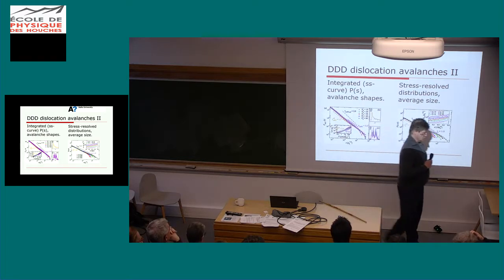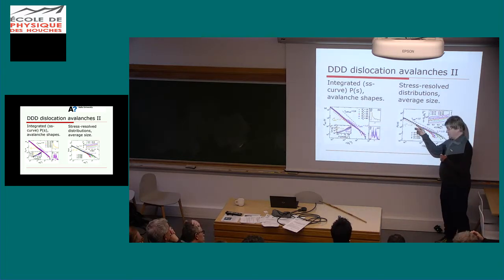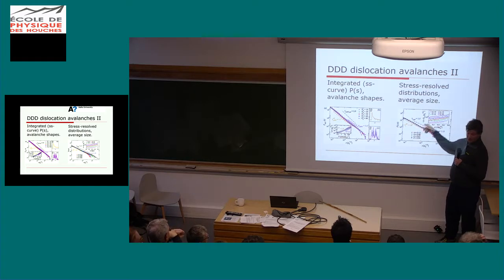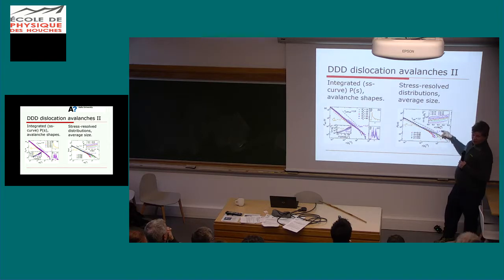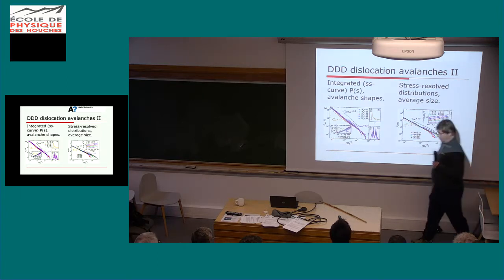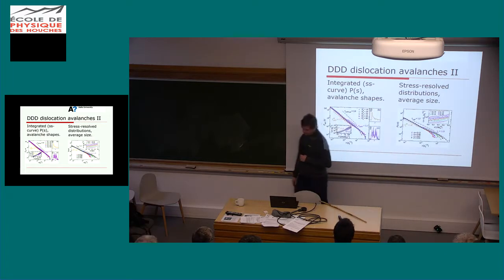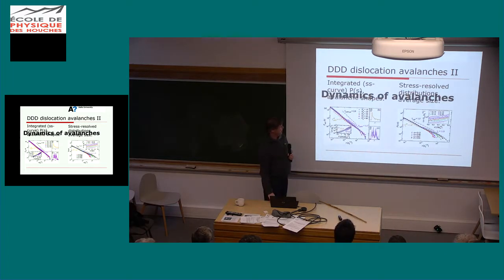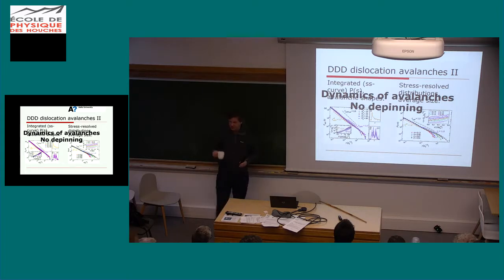The last of these plots shows the same thing again, in the sense that at small ranges, since it's a 3D system, you get something strange because only single segments participate in the avalanche. At larger scales the exponent goes down and the participation number is large. If you consider the typical avalanche size as a function of the external stress that you apply and the number of dislocations in your system, it has the same kind of feature as in the 2D case. One point here is the dynamics of avalanches. The second point is quite simply that there's no depinning here either. And this is supposed to be a realistic crystal.